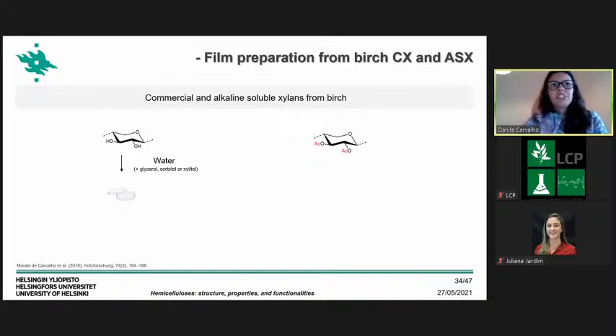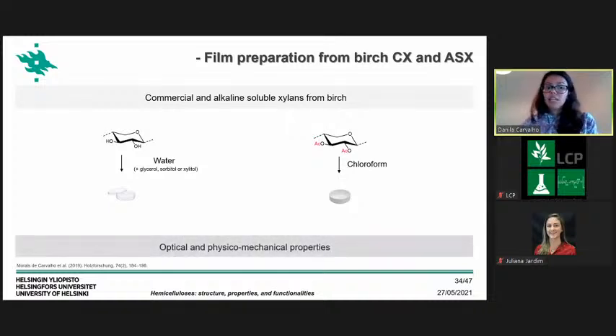And according to the literature, it's very difficult to form a continuous film without using some plasticizer. That's why we also applied three different plasticizers to check the possibility of forming these films. We used glycerol, sorbitol, and xylitol. And for the acetylated xylan, we cast the films using chloroform as the medium. And then later, we tested the optical and physical-mechanical properties.